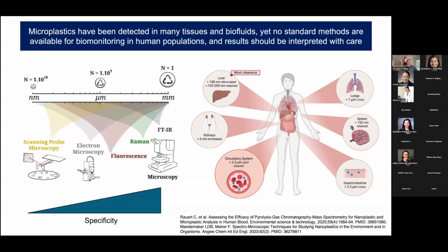And so the most common approaches that have been used are things like FTIR or Raman spectroscopy, which allow you to both image a particle and look at the spectra from it to identify what the underlying polymer is. Unfortunately, these often are limited by resolution and do not allow us to measure particles that are smaller than 1 to 5 micron. And so it's really not capturing that nanoplastic range. Of course, we can use things like electron microscopy or scanning probe microscopy to do that, but that only allows us to visualize the particles. It doesn't give us any chemical composition information. So we can't actually confirm the particle we're seeing is a plastic.